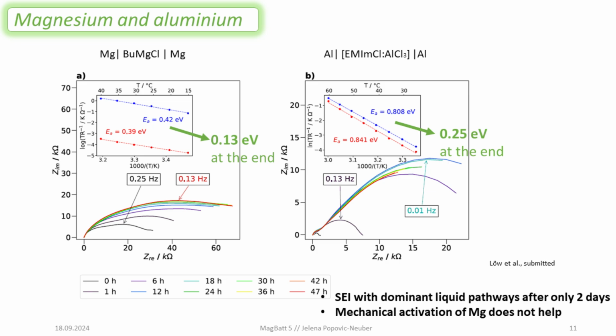In the case of aluminium, it's the same, more or less. In the case of aluminium, it's also known that these kind of electrolytes are quite corrosive towards the native films of aluminium. So it's quite interesting that in this case, again, we go from 0.8 to 0.25 electron volts. So interesting findings in magnesium and aluminium, very, very different than the lithium and sodium cases. So please go and talk with Mario.